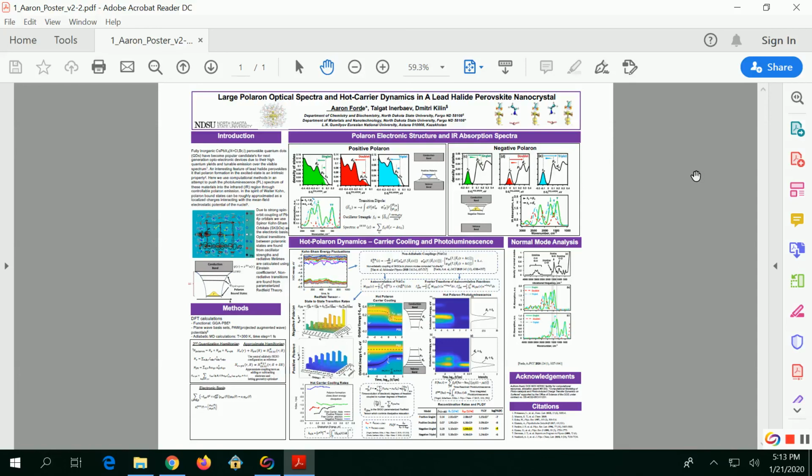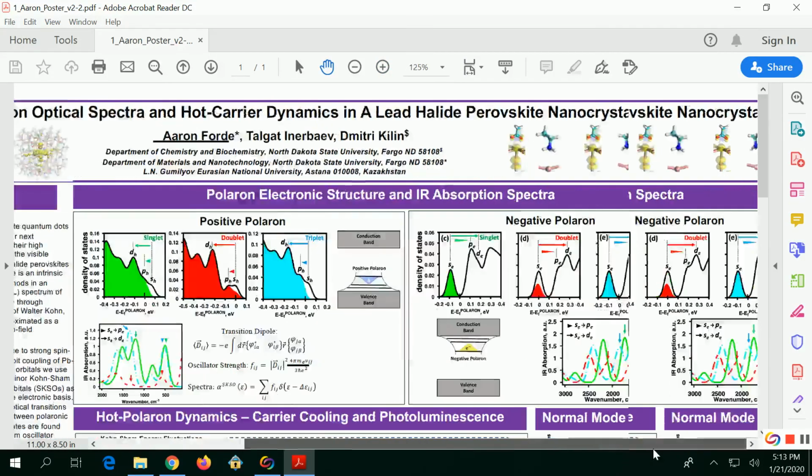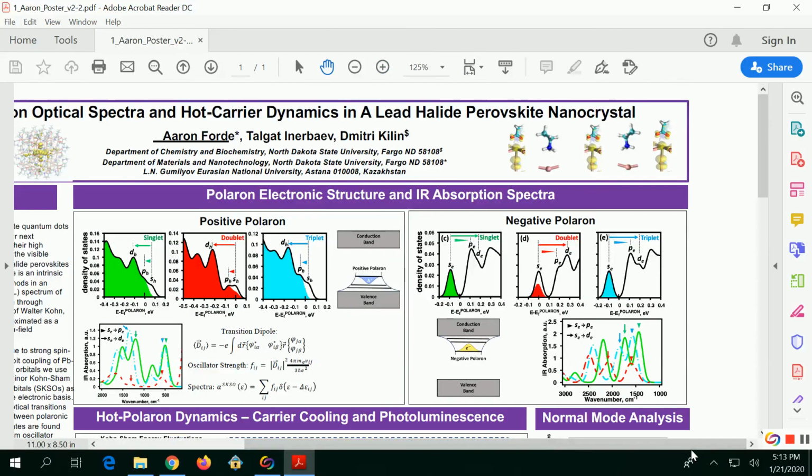The reason I'm asking this is that your unoccupied orbitals are typically anti-bonding. Right, so anti-bonding is destabilizing. So if you're in an orbital that initially has anti-bonding character, then you should expect it to pop off.